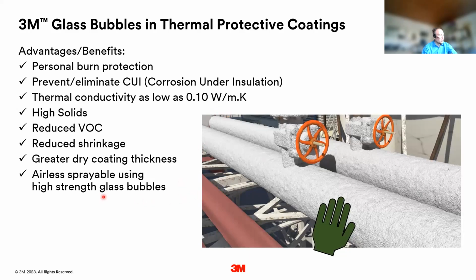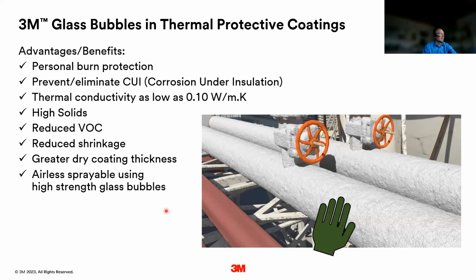Again, with using the right bubbles, such coatings can also be applied by airless spraying, and there's the benefit that it can easily be repaired. So, for instance, if you have maintenance, like at a valve or whatever, you scratch off the coating, and afterwards you just repair the coating after you exchange the valve, for instance.